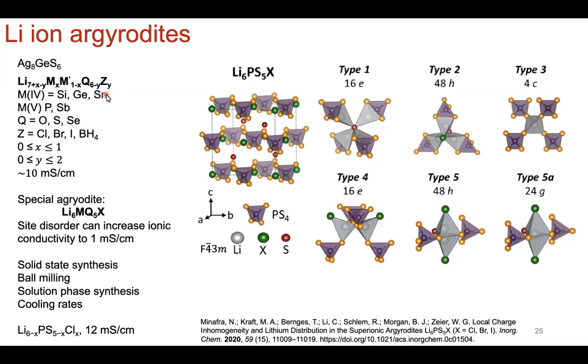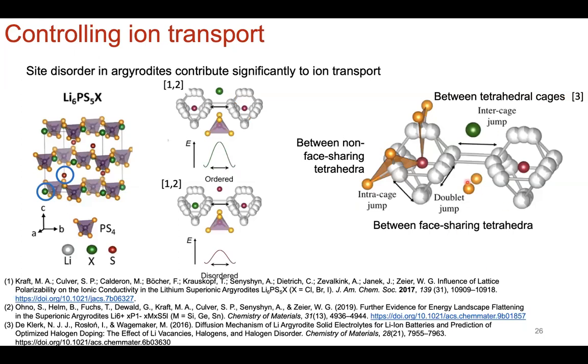Now, instead of talking about all the possible compositions, what I'll talk about is one of the compounds that has been studied widely, which is Li6MQ5X. So the chalcogenide sits here, and it's typically a sulfur, although there's been sulfur-selenium mixing for anion disorder type of studies. But what's really interesting about this compound is that if you look at where the lithium sites are, there are many pathways. There are many sites for lithium ions to sit. And so that also means there are many pathways for ion migration, but the typical pathway really is this doublet jump between the two cages, or between the two tetrahedra.